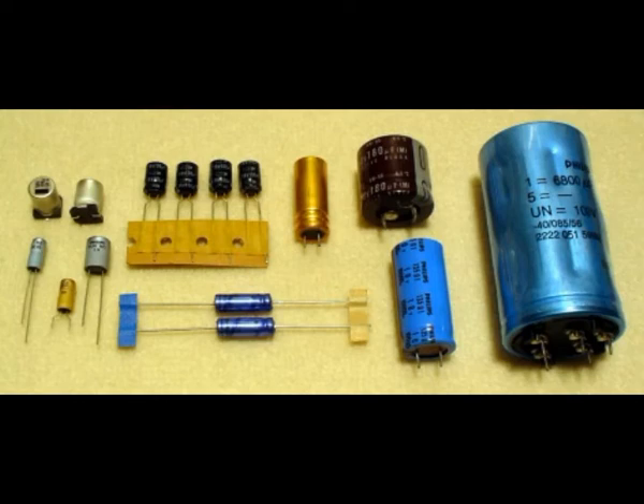short circuit, open circuit, and on the other hand, not reaching degradation failure, a reduction of capacitance over 30% and an increase of the ESR, impedance or loss factor by more than a factor of 3 compared to the initial value. Parameters of the tested component beyond these limits can be counted as evidence of degradation failure. The testing time and temperature depend on the tested series.